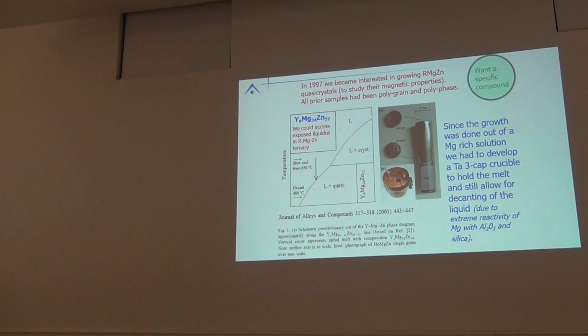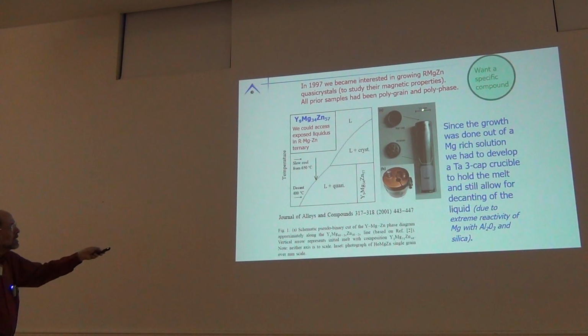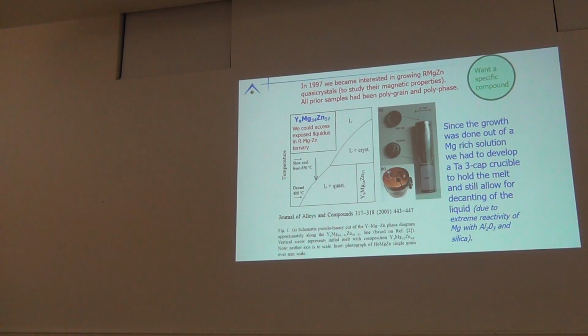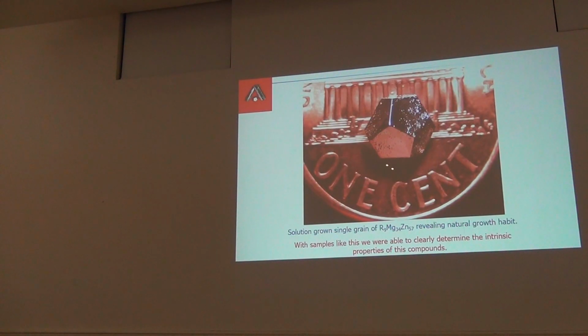We had to develop a way of holding it. This is when we developed this 3-cap tantalum crucible, okay? Tantalum tube, you weld a cap in the bottom, you have a cap in between that you drill holes in to be the filter, and then you weld a cap on the top. This is done in the arc melter. This allows you to hold the material, you heat it up, you cool it, you decant, and you end up with single crystals that look like this, okay?